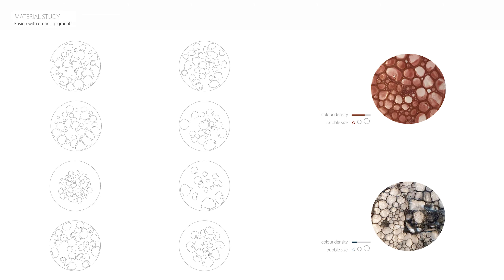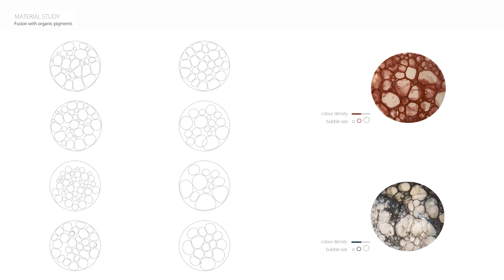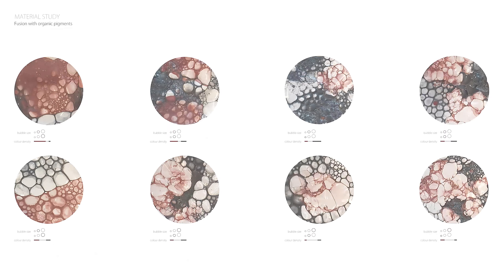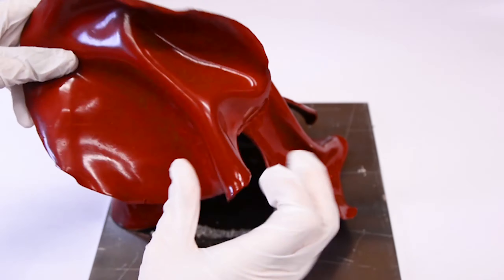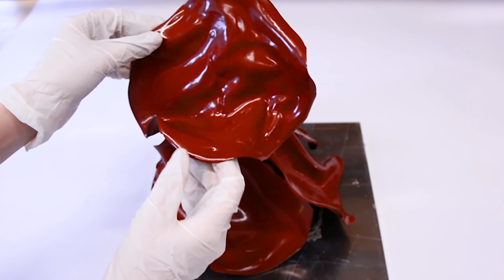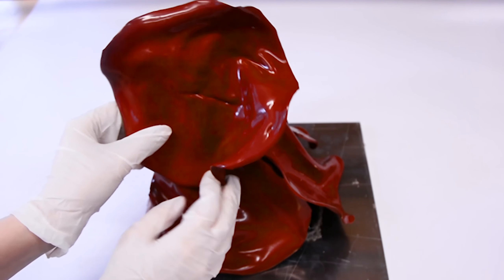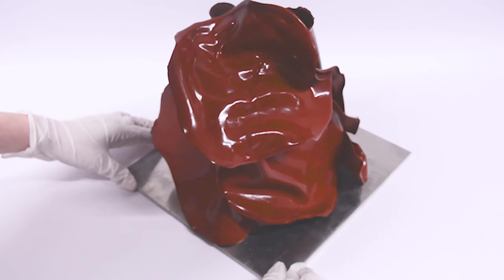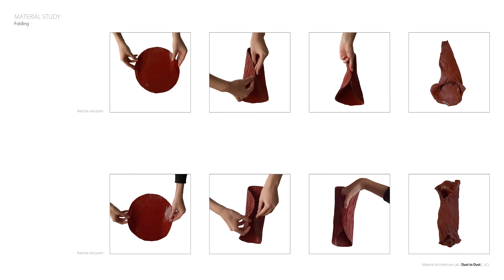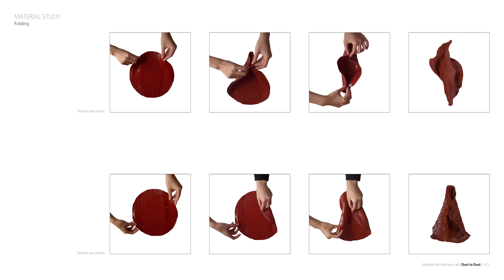This material can change its color and hardness through pigments. We have tried using mineral pigments in order to achieve a stiffer surface and clearer organic patterns. Different shaped molds can then be used to define the form and texture of the resulting object. High flexibility is a key property. The flexibility of the material is dependent on changes in air temperature and heat, melting and flattening as the temperature rises, curling and shrinking when cooled. Because of its shrinkage properties, shaping and folding applied to soft materials can be maintained until the material is fully dehydrated and hardened.